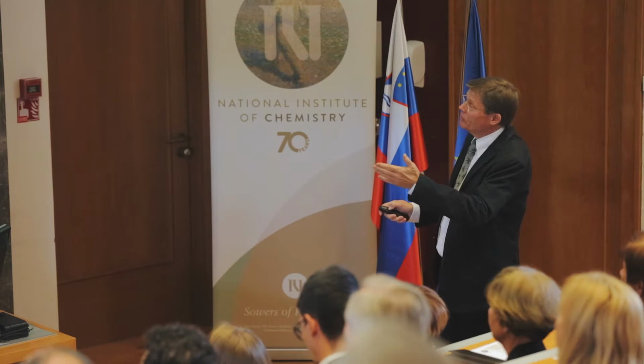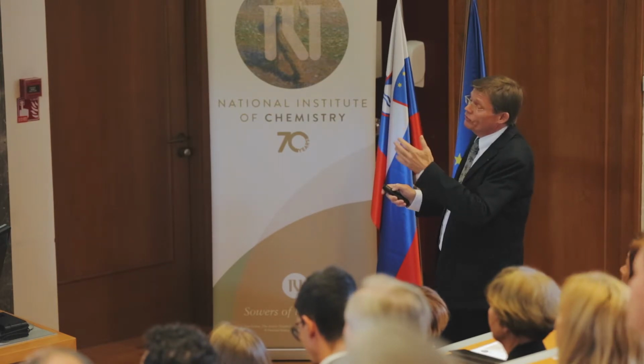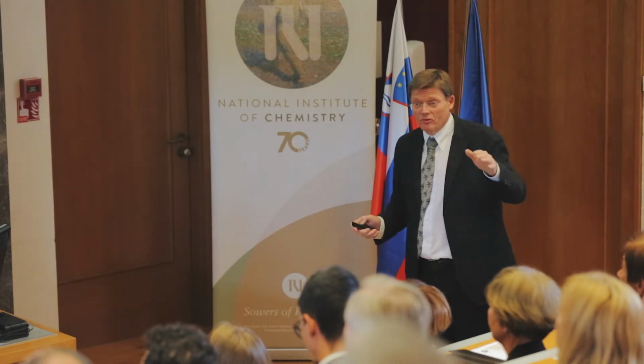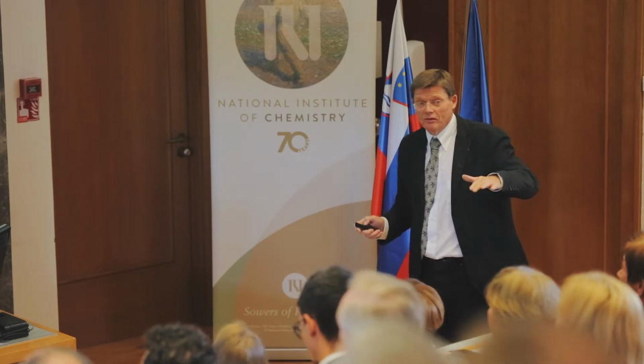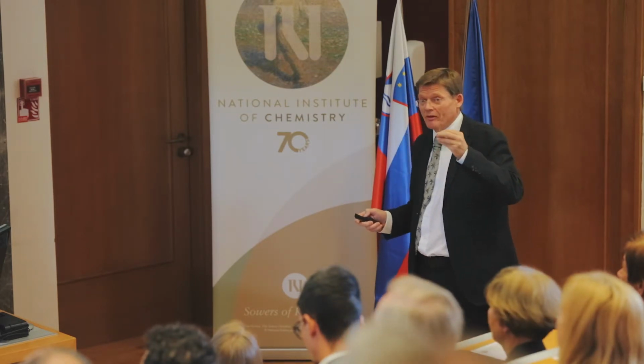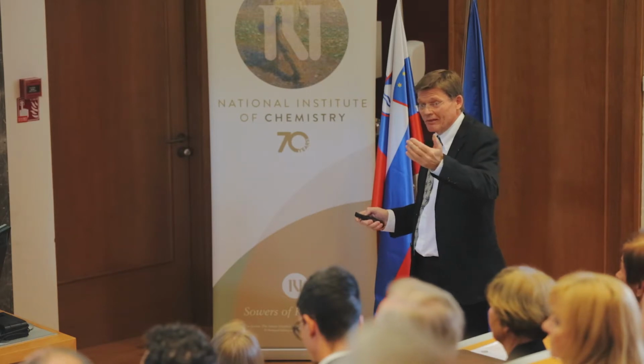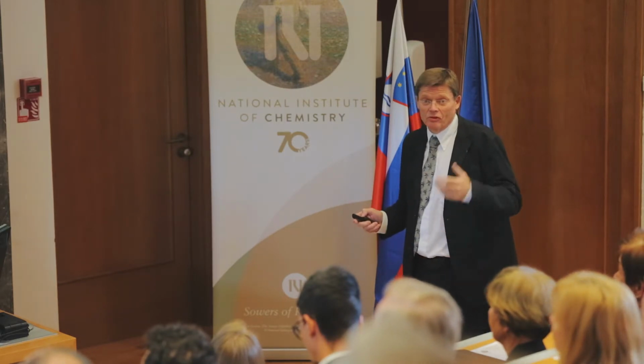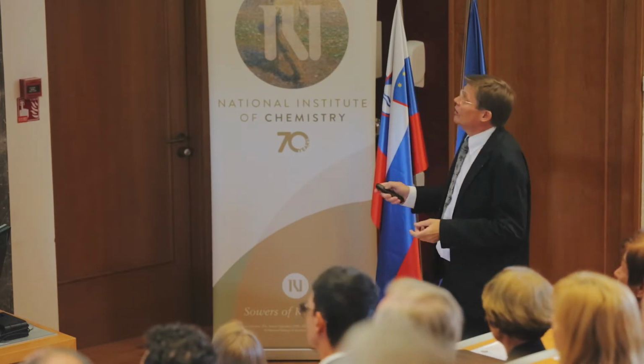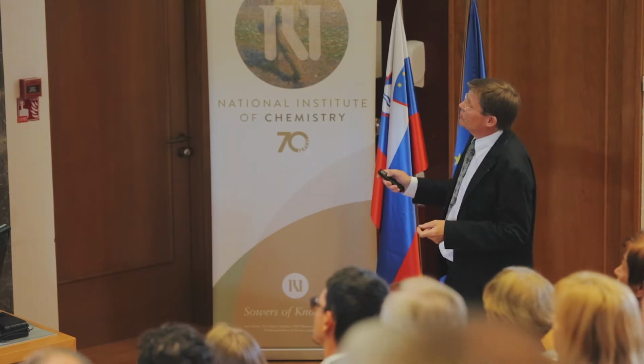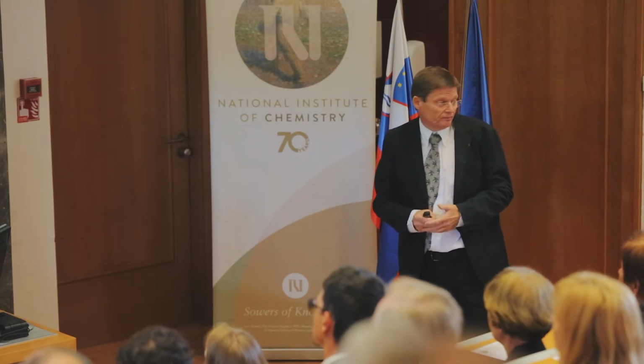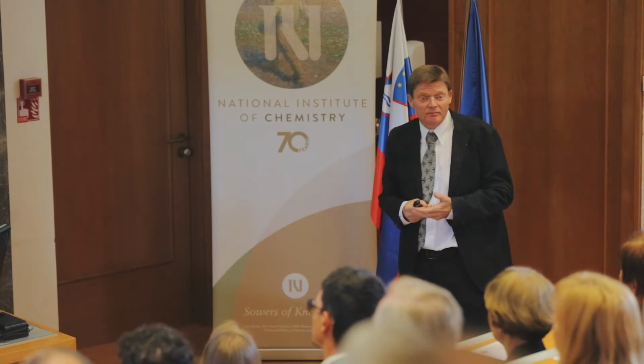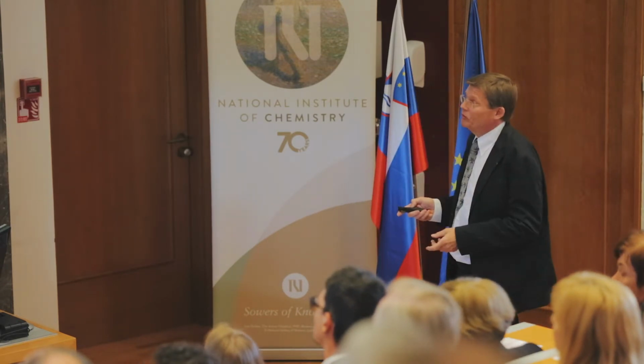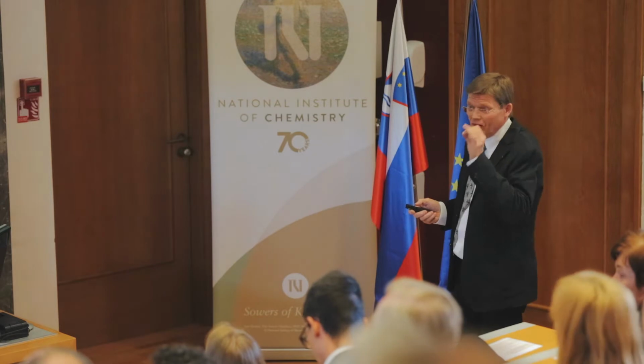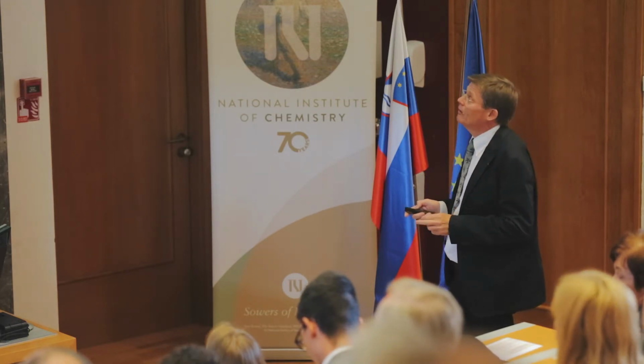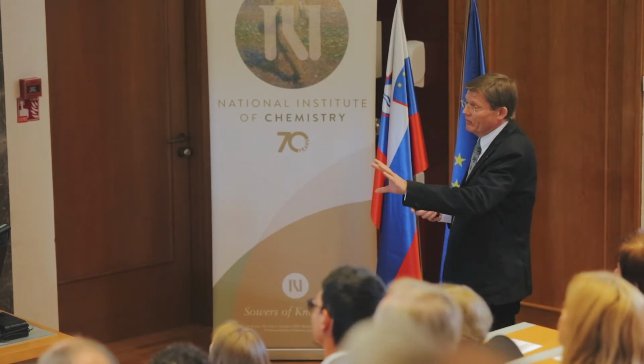So when the iodine partial pressure is increased, you fill your iodine vacancies, so you decrease your ionic conductivity. But iodine is incorporated as iodide, so it takes two electrons, so you increase the hole concentration. So electron conductivity goes up, ion conductivity goes down. This is very simple. But it's hard to bring this over to the community that is not thinking in terms of mixed conductivity. So this was a time picture.